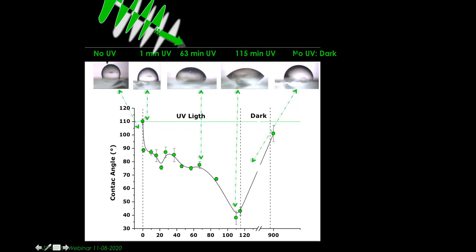And when you remove the UV, that droplet comes back to its initial status. And if you shine again, you would go towards this. And if you remove the UV, it goes back to its initial state. So by changing the contact angle, as you can see, we change the surface tension of the liquid. And that is a confirmation of the tunability of a thermodynamic macroscopic parameter, which is the surface tension.